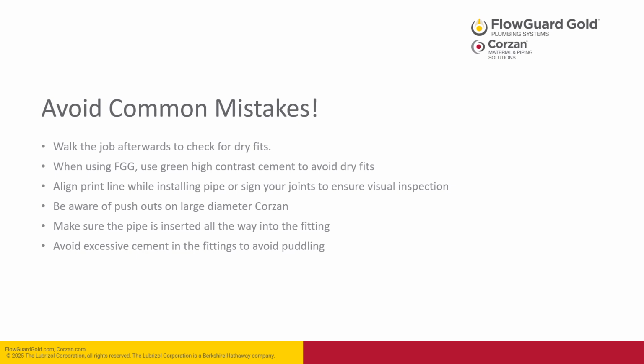Because of that interference fit and the liquid of the solvent cement, it is possible for the pipe to back out from the fitting after being inserted. This is why on large diameters it's recommended to use a pipe puller or come-along.